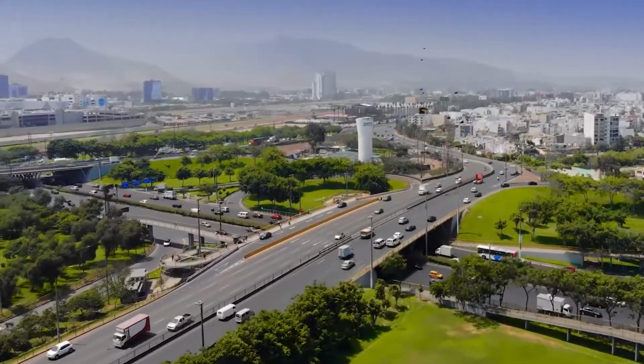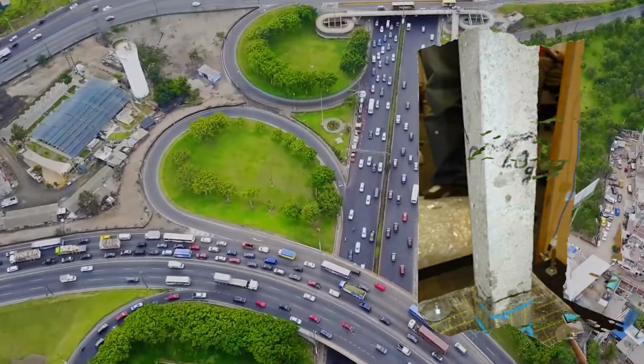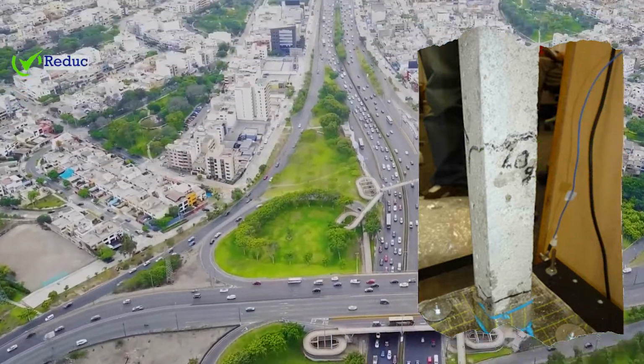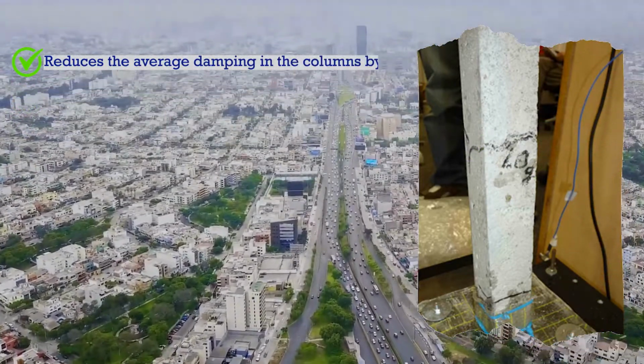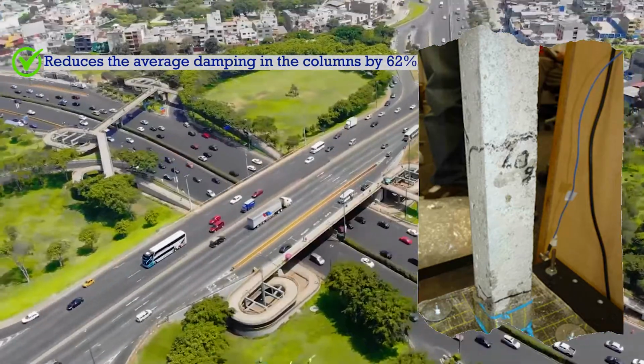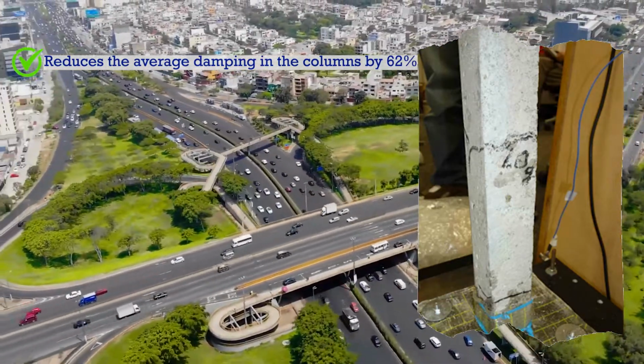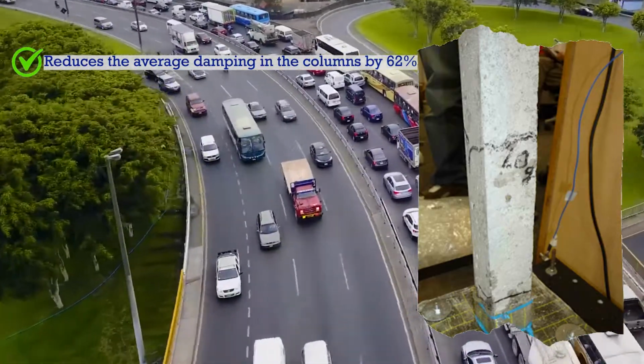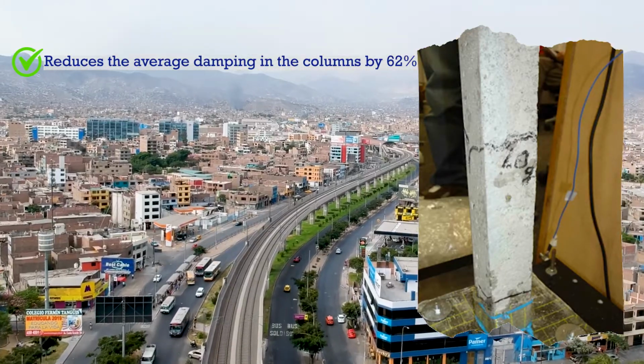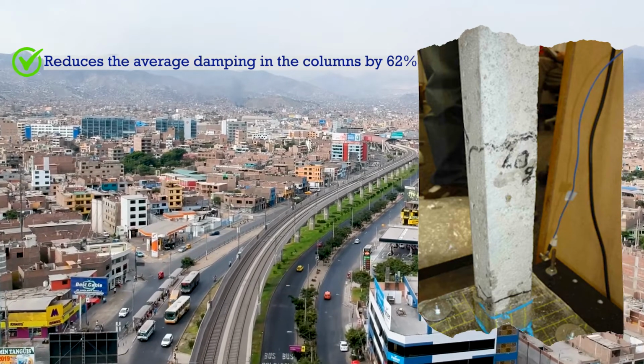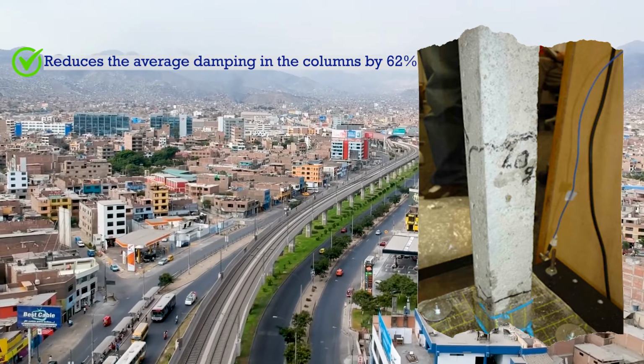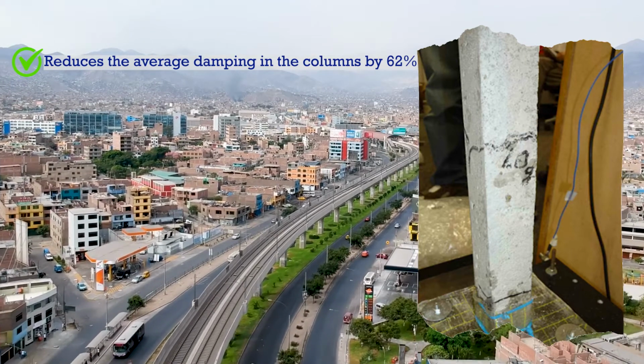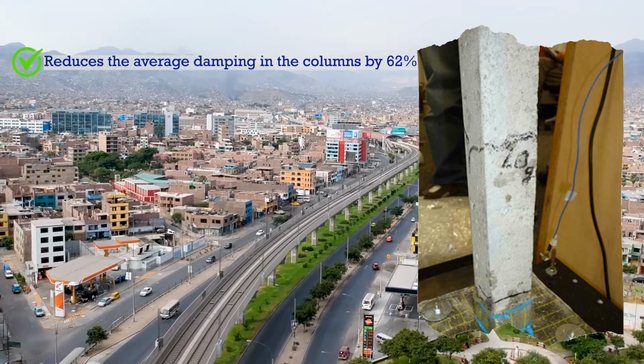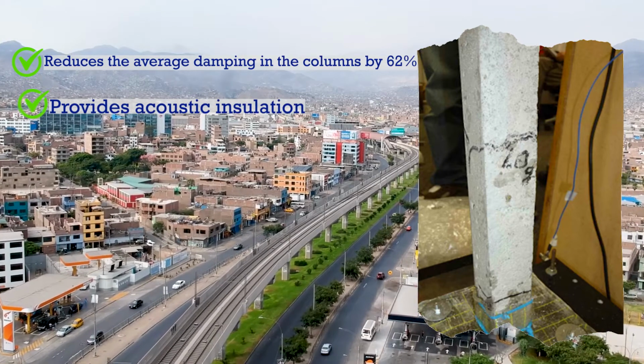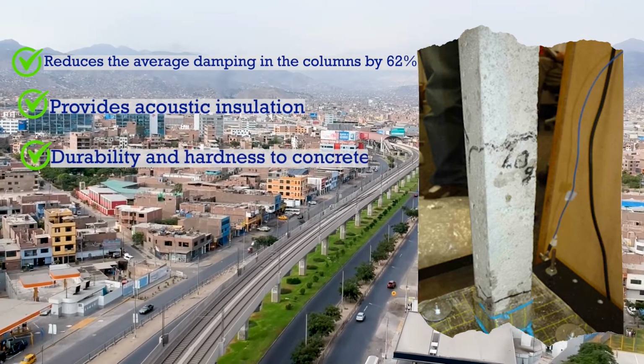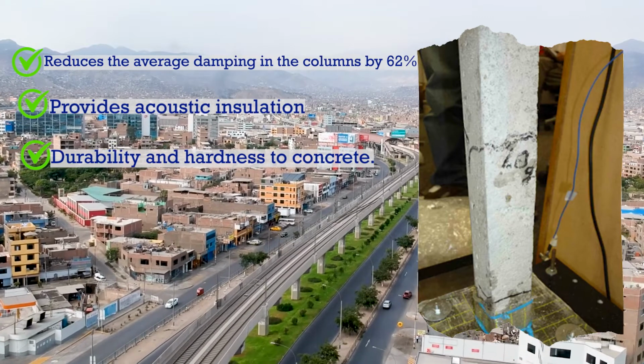Additionally, rubber gives concrete some interesting anti-seismic properties. Rubberized concrete reduces the average damping in the columns by 62% and reduces the seismic force. However, it has low compressive strength, up to 40-70% less than conventional concrete. That is because the rubber absorbs plastic energy and the bond between rubber and cement is poor. Fortunately, there are additions like silica fume that improve this feature. Rubber also provides the concrete with properties such as acoustic insulation, greater durability, and greater hardness.